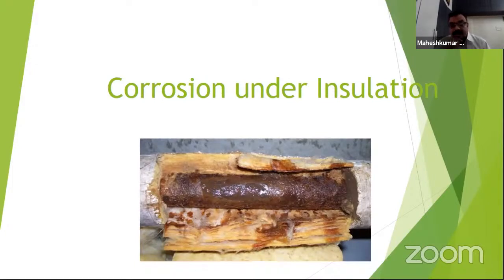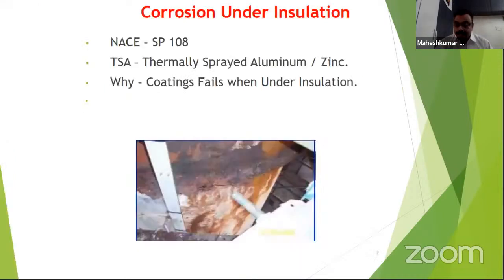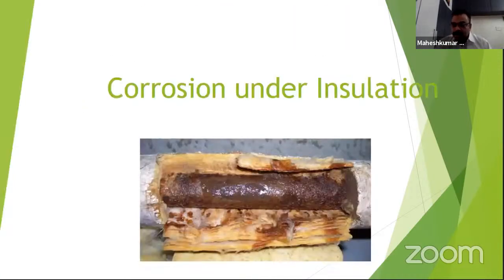You can see the insulation is made with rock wool. Now, if this rock wool is used, or say sponge, or polyurethane foam, or any other type of insulation, it has a capacity for moisture to be absorbed in it. Once the pipeline is heated, it becomes dry. Once the pipeline goes back down in temperature, condensation starts. With condensation, all the moisture sits in the insulated pipeline. This moisture goes down to the surface.